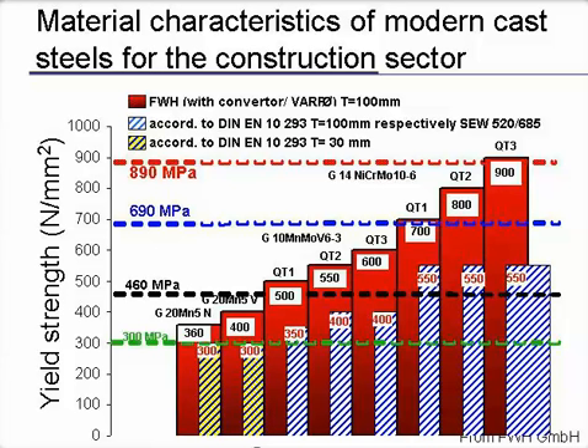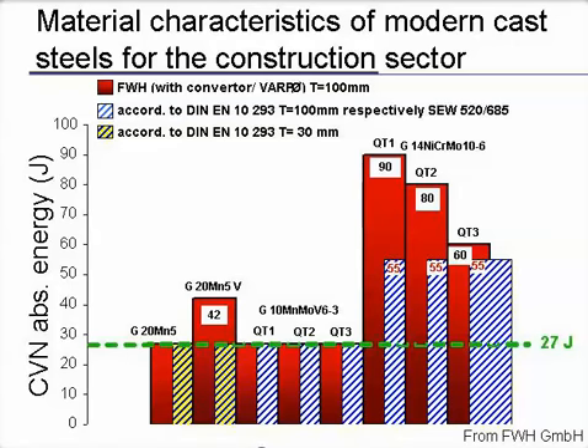Right now they are not used or very little used in the construction sector, but there is research going on now to use more and more of these. They are used, in fact, mainly in mechanical applications, a little bit in construction for housing of cables and things like that, but not for nodes in buildings or bridges. And to further show you that there is no problem with toughness, this is still very good toughness. You see 27 joules here, and you see the values that you can get according to the code, what you need and what you get with these steels. So it's no problem. They are very, very tough.